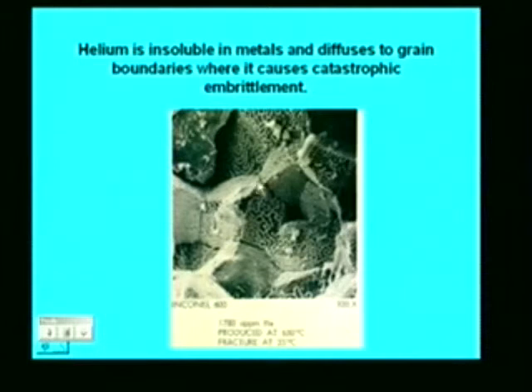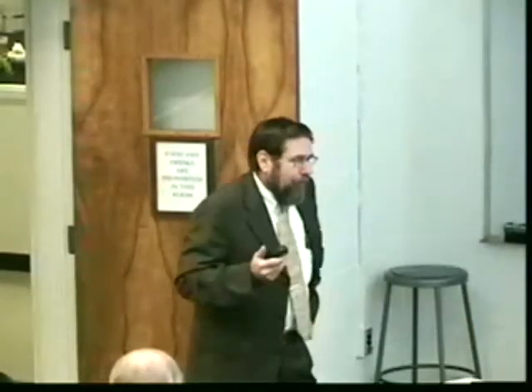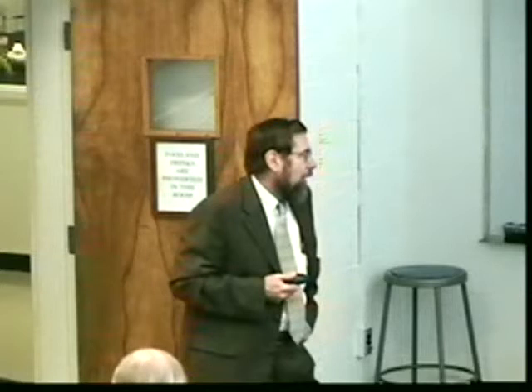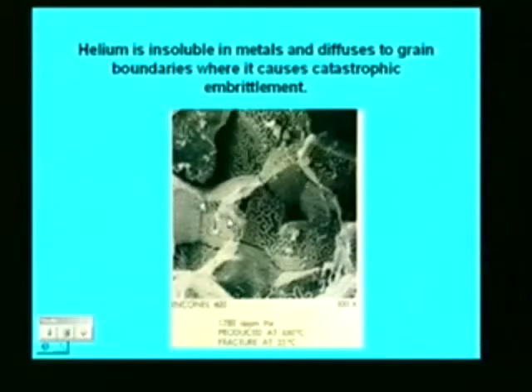But you'll also notice that the boundaries are completely covered with bubbles. And this material is Inconel 600. It's a high-temperature nickel alloy. Used to be popular steam generator material, though there you don't have a neutron flux to worry about. It has been irradiated in the High Flux Isotope Reactor at Oak Ridge, producing about 1,800 ppm helium through the two-step nickel reaction at 650C. And this is probably one of the worst cases of helium embrittlement I've seen. You can continue irradiation and probably make it fall apart on the grain boundaries and produce metallic sand, if you like.